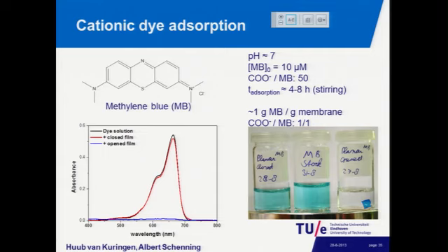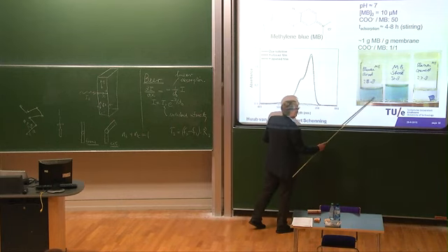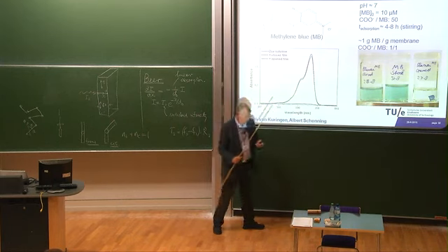We have a small piece of this film. We throw it in a solution containing this dye. We just wait a few hours, and all the dye is collected into the polymer film. If we have not opened the pores by this alkaline treatment, this is a reference, it does not happen. So you have a very effective means to